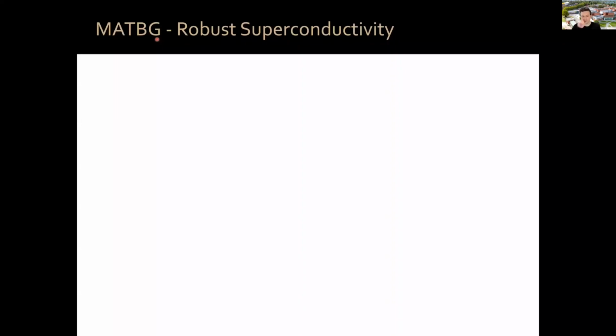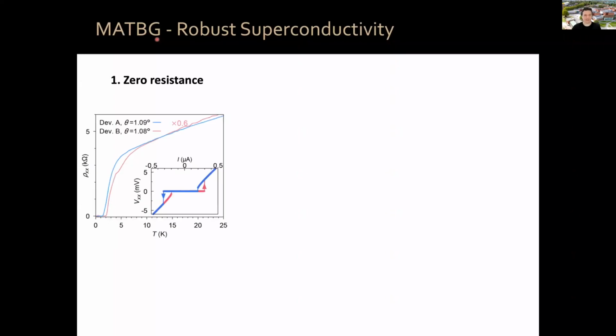Okay, and what do I mean by robust superconductivity? First, the system has to exhibit zero resistance. So these are data for two recent devices where the resistance goes down to zero, as well as you can measure zero. And if you measure the VI curves, you have these flat VI curves.